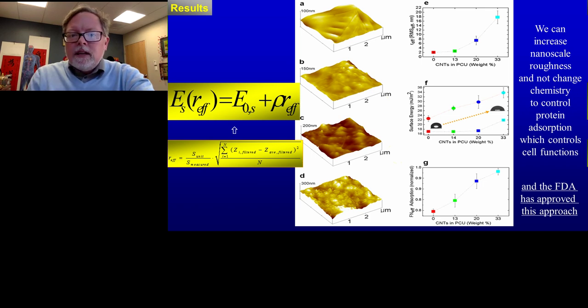And that's what's shown in the graph on E, basically going from 0 weight percent carbon nanotubes in polyurethane, which is letter A, to 13 weight percent, which is letter B, to 20 weight percent, which is letter C, and then to 33 weight percent, which is letter D. So of course we see an increase of roughness the more carbon nanotubes we add. If you then look at the graph in F, that shows you the change of contact angle, or the change of energy, you're getting when you increase nanoscale features. So simply going from, again, 0 to 33 weight percent carbon nanotube, going from the image in A to the image in D, we get a more hydrophilic surface. That water drop is spreading more when we have more nanoscale features.